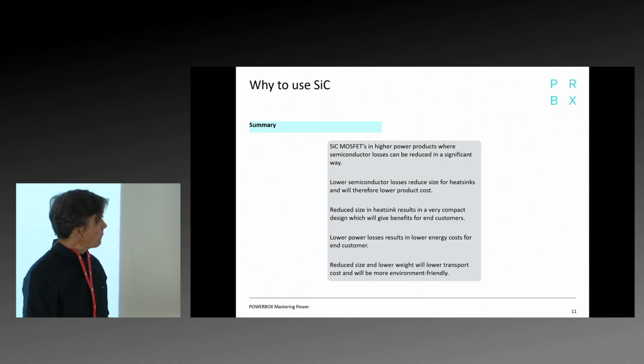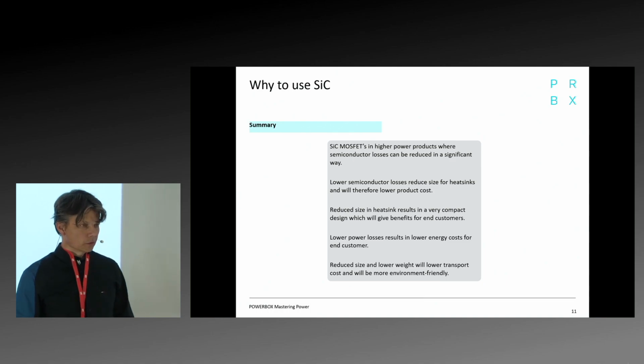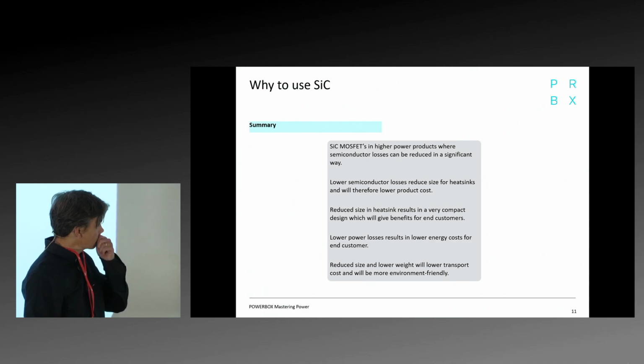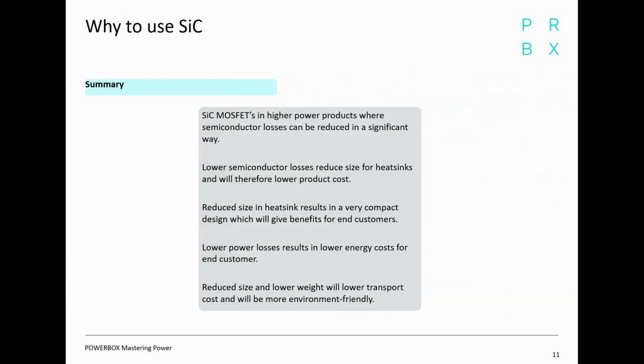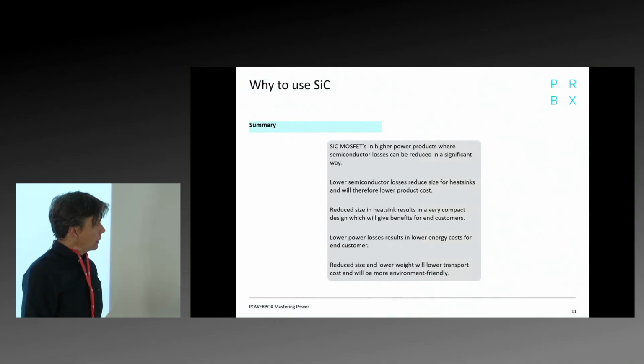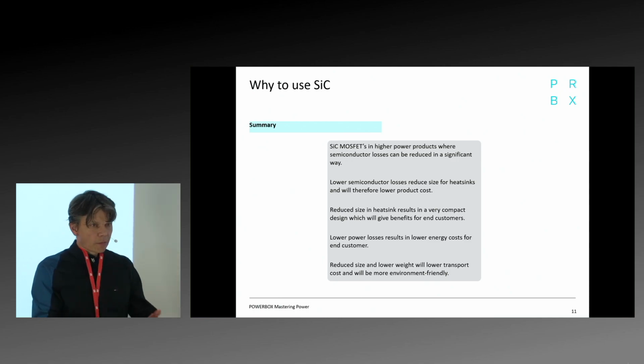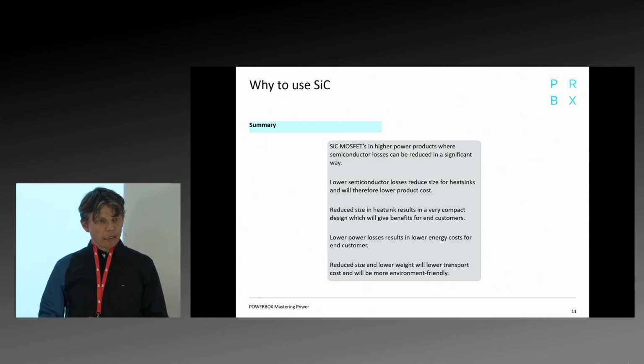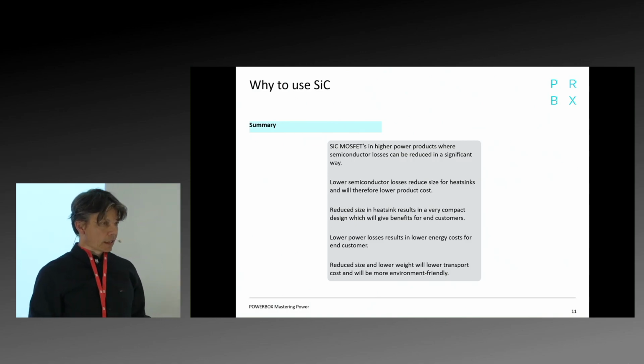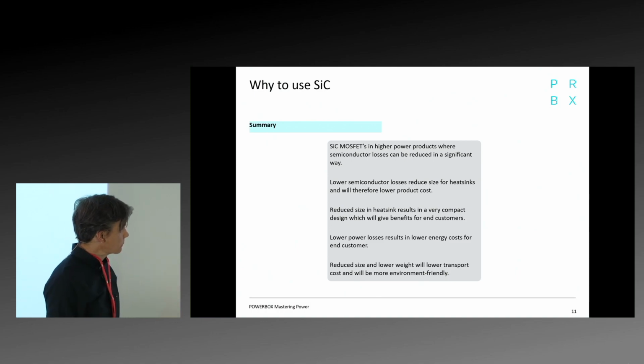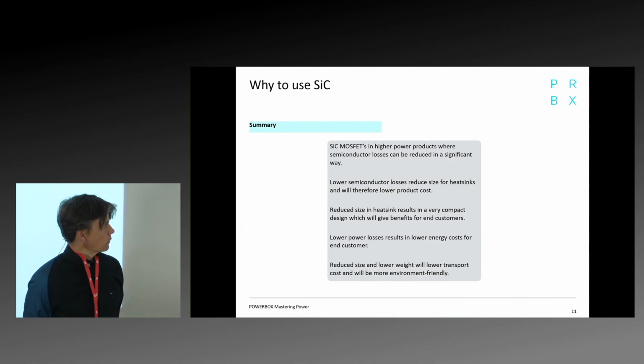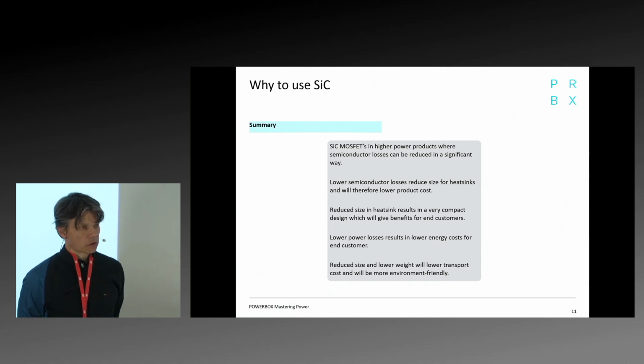And then finally the summary of why to use silicon carbide: should we use silicon carbide or should we use silicon? In higher power products, it is easier to see that silicon carbide has a lot of benefits and we can reduce the losses a lot. So there it will be quite simple. Then of course there will be some gray zone in between. There it maybe needs more investigation to finally select whether we go further with silicon or silicon carbide. But as I mentioned, the big benefit is to reduce the size of heat sinks, and that will also reduce the product cost.